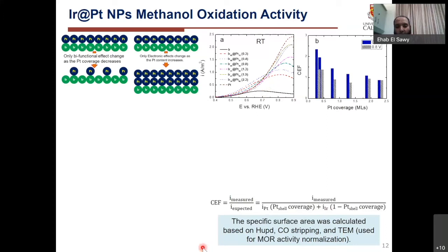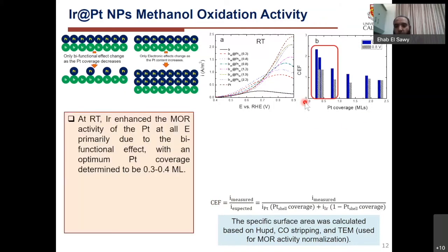So we calculated the expected current as if we were mixing them, with the surfaces mixed separately, and compared it with the measured current, which integrates the synergistic effect. We come up with a factor called the catalytic enhancement factor. At low coverage, the catalytic enhancement factor was high, indicating that exposing the iridium to the solution will enhance the oxidation of carbon monoxide, which is an intermediate, and therefore enhance the catalytic activity of the platinum.